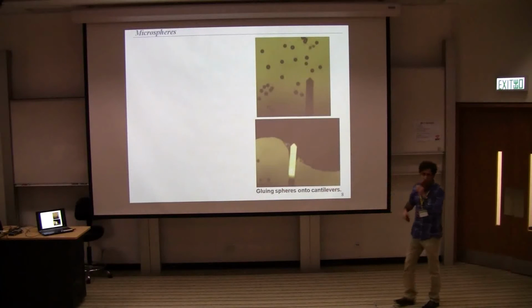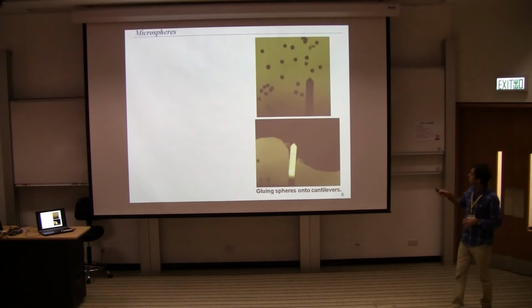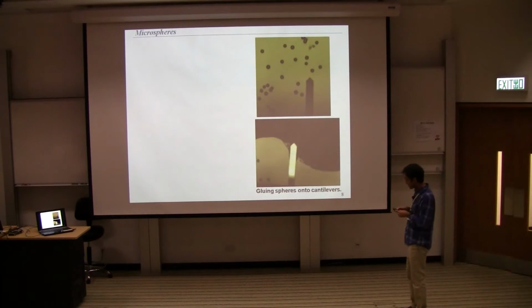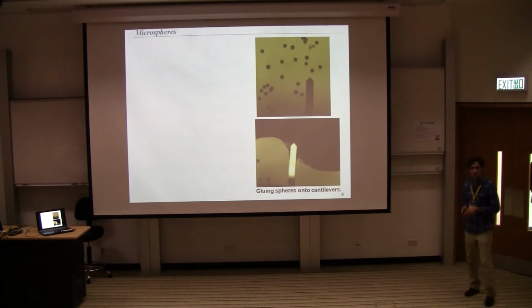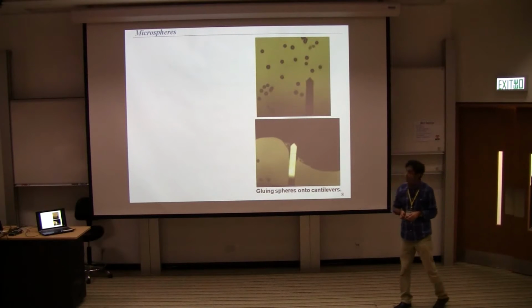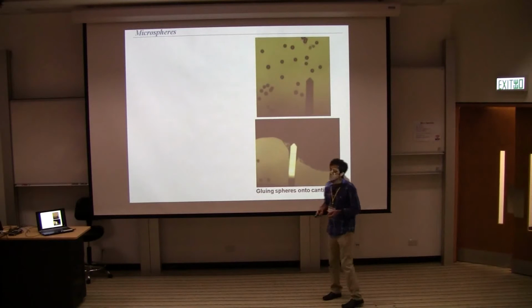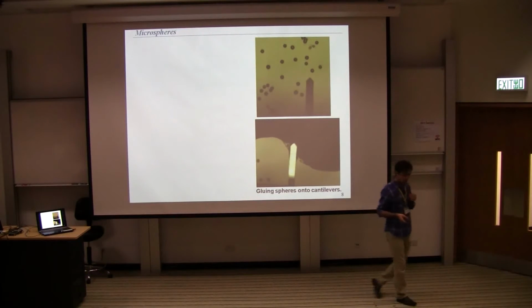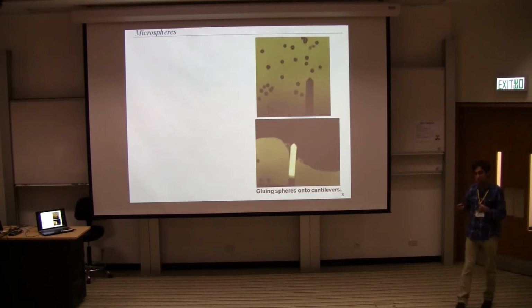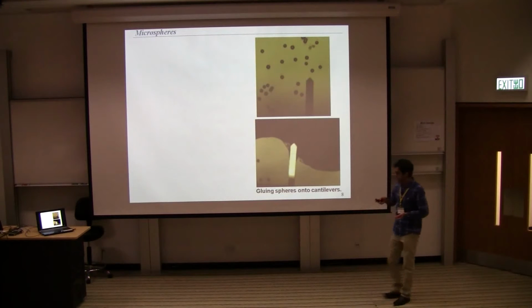From here, I want to focus more on the process we use for Casimir force measurement. Here we see the cantilever and the sphere under the optical microscope of the AFM. We use a borosilicate sphere with a 10 micrometer radius and attach it to the cantilever. It's a little bit tricky and time-consuming process, and you should also be a little bit lucky to get a clean sphere and a smooth interaction slab.